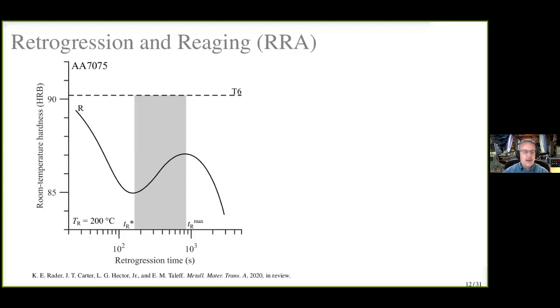So that's represented here as the room temperature hardness measurement as a function of the retrogression time on the horizontal axis on a logarithmic scale, all for this temperature of 200 degrees Celsius. So we basically are applying this temperature for this retrogression time. We cool the material down and we measure the hardness. In the T6 condition, we're up here above 90 Rockwell B hardness. After we retrogress for about 20 seconds or so, you can see the hardness drops down. So R is the retrogressed curve.